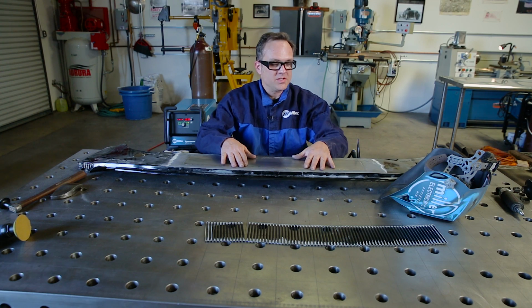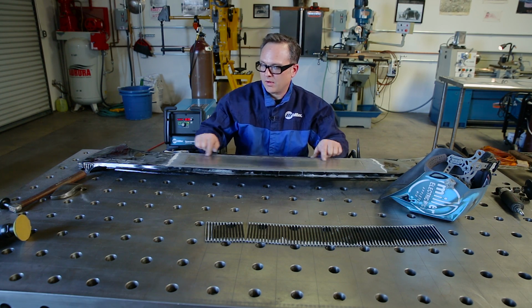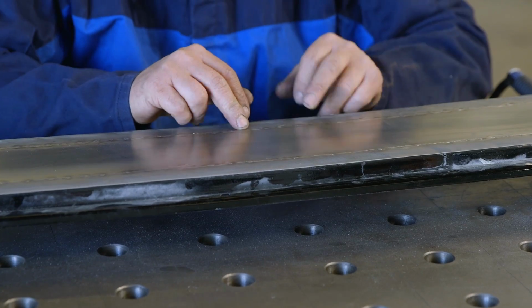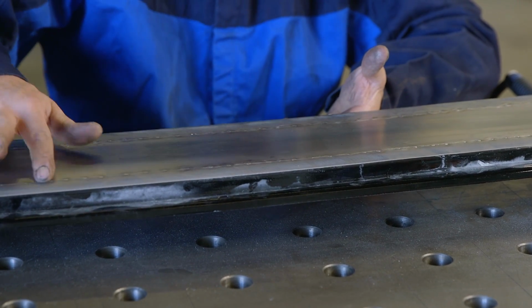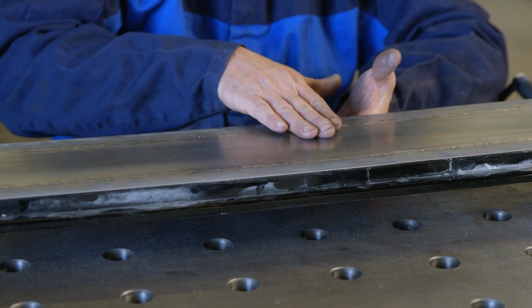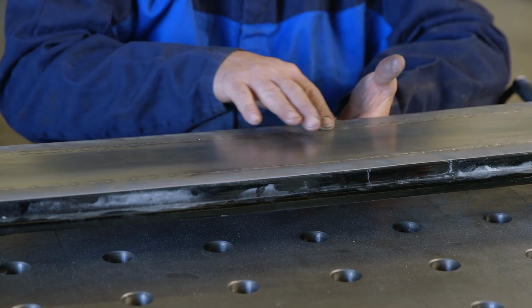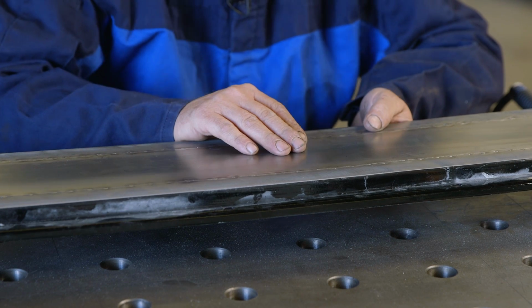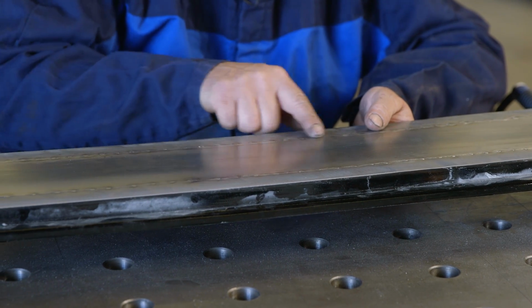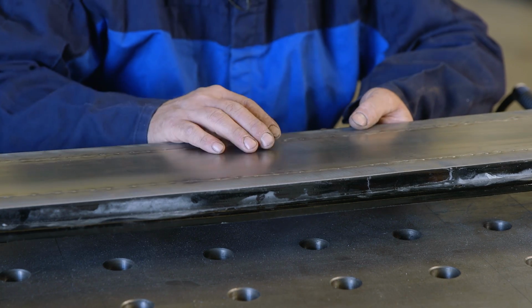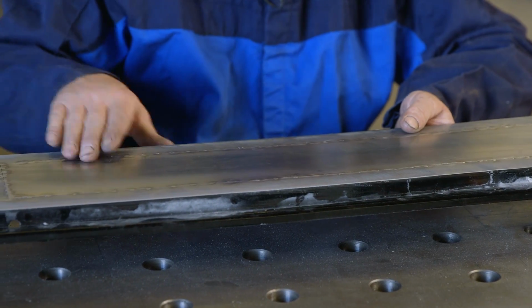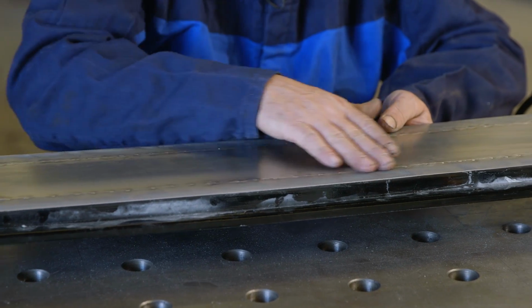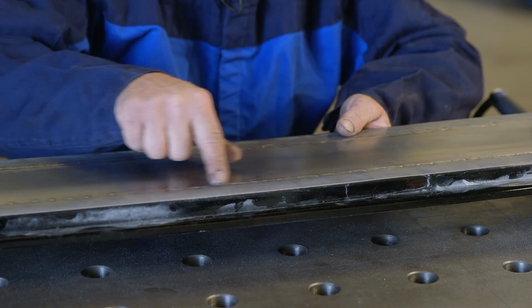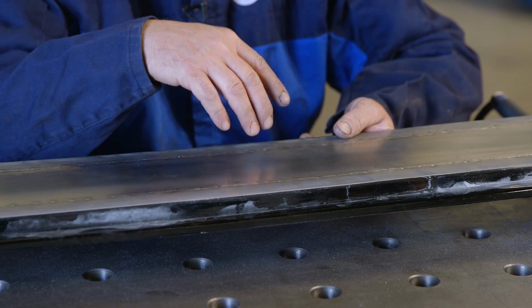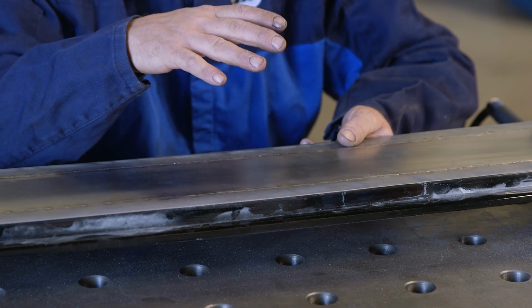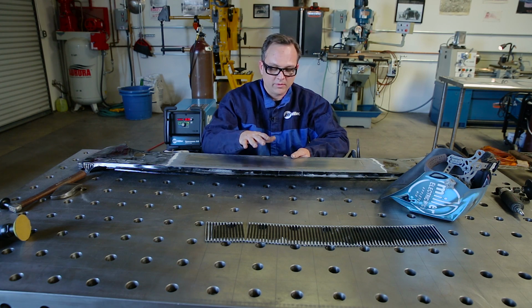So now I have tacked the piece in about every 3/4 of an inch. I have a tack all the way around. I hammered it flat with a hammer and dolly to make sure that I don't have any high and low spots. You want the top of the two pieces flush with each other before you start welding. Also, I ground off just the high spots of the tacks. It just helps later on. And I used some Scotch-Brite. You can use Scotch-Brite or sandpaper and actually clean the weld so that it gets rid of the coloration on it, which is oxidation, which can also contaminate. If you always have it as clean as possible, you're gonna have less problems.